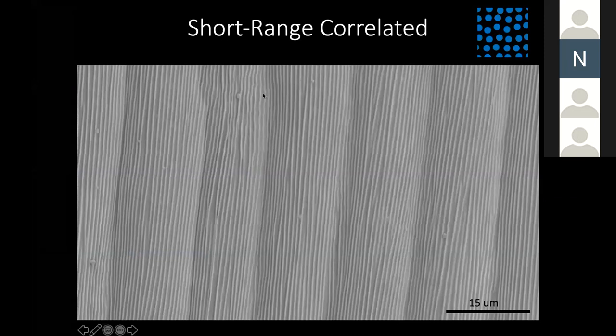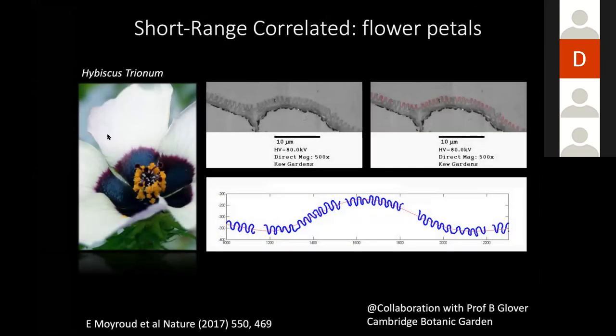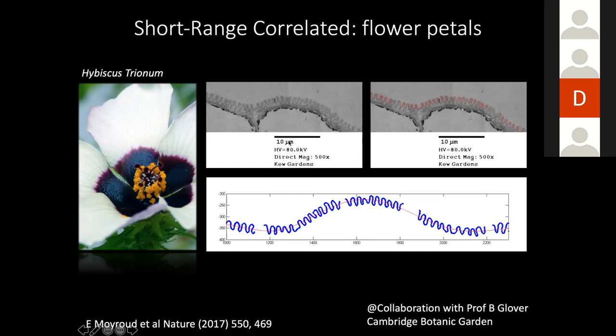This is an SEM of a petal of a flower, which is called the hibiscus. And if you look at this picture, you see that you have this blue tint that is coming from the base of the petal. And this blue tint is essentially the result of this modulation of the cuticle of the flower petal itself. And these are TEM images where you can see in cross section how the petal surface looks like. So what is interesting is that if you make replicas, they have the same degree of disorder,